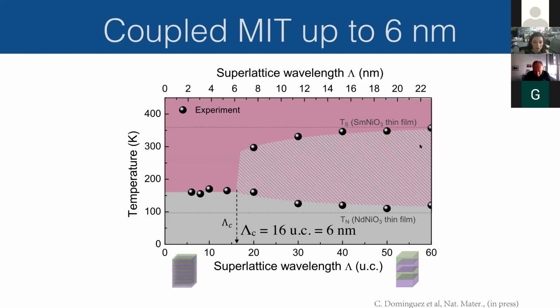This phase diagram summarizes the same data, but with a few more points. So here you see the transitions are these black dots, and they are separated at high lambda, so thick layers, and then they come together in temperature until you just have one transition for low lambda. Now, what is interesting is the lambda at which you see this coming together of the transition. So this is happening at 16 unit cells, or 6 nanometers. And this is something that we wanted to understand. Why is this number what it is?